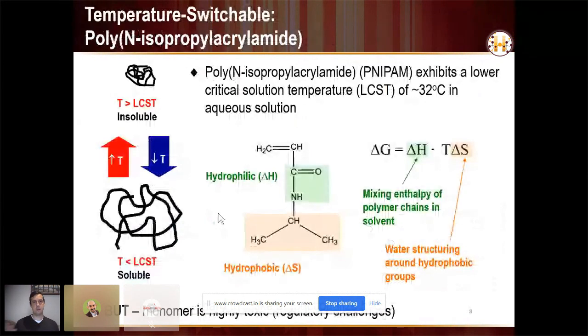There's also a lot of interest in making these temperature switchable polymers, and the key polymer there is poly(N-isopropyl acrylamide). And this is a polymer that exhibits what's called a lower critical solution temperature in aqueous solution. This is really interesting thermodynamic behavior driven by the interesting structure of this monomer, where we have a hydrophilic hydrogen bonding group and a hydrophobic group, the isopropyl group on the end. So as we heat up the temperature, based on Gibbs free energy, the entropically driven transition, which is the self-assembly, the hydrophobic assembly of the isopropyl groups, begins to become more and more dominant over the enthalpic component, which is the hydrogen bonding. And we actually induce a phase separation, a physical phase transition. And again, this is completely reversible as we move the temperature up and down.